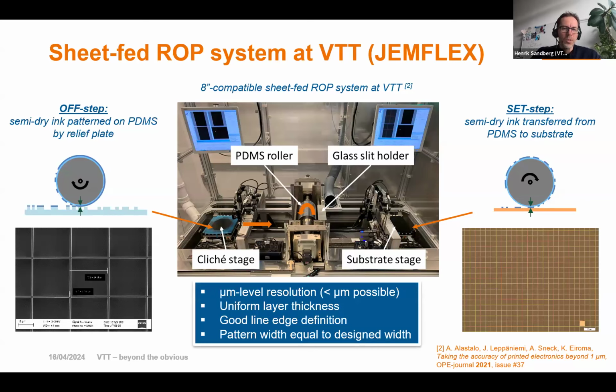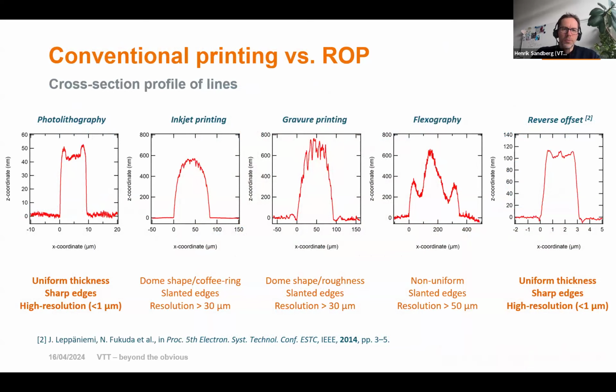a similar positional accuracy. Then the layer thickness is low because we apply a very thin layer of this material onto the roller. And the line edge definition is also on a very high level in this method, which is one of the big advantages. And if we look into the edge definition of many other printed methods, for example, we see that there are all kinds of issues with most of the printed electronics additive methods, but the reverse offset, which is on the right, actually reaches a very similar edge definition quality as photolithography. So this also means that we can, by printing, target similar applications as currently require photolithography.